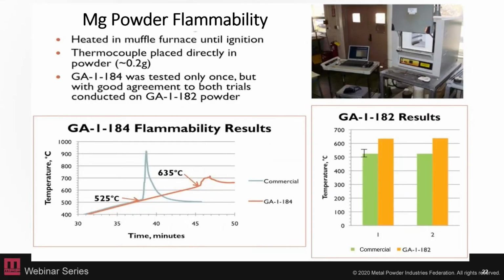One example that we have done in-house, as I'm wrapping up here, is magnesium powder flammability. Traditionally, you would think of magnesium as one of the more reactive materials, with all of the materials on the left side of the periodic table increasing in reactivity. However, with this powder, we were focused specifically on the surface as we were atomizing this powder, and made an oxyfluoride coating rather than just an oxide coating, as the oxyfluoride is more stable than the oxide.